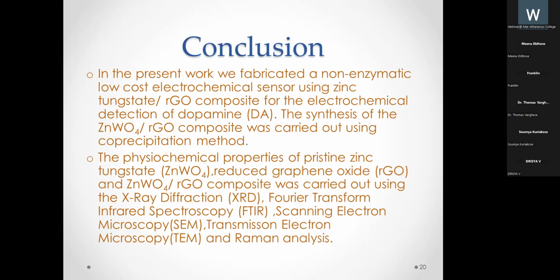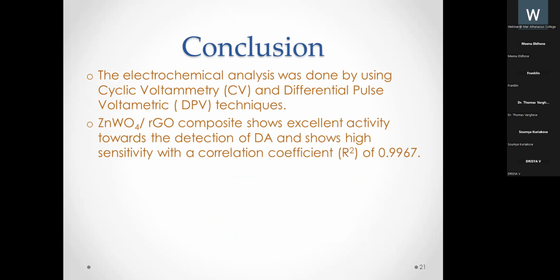The major conclusion which I have arrived at is that in the present work, we fabricated a non-enzymatic, low-cost electrochemical sensor for the electrochemical detection of dopamine. The synthesis was very simple, carried out using the co-precipitation method for the zinc tungstate RGO composite. The physicochemical properties of pristine zinc tungstate, reduced graphene oxide, and zinc tungstate composites were studied using XRD, FTIR, scanning electron microscopy, TEM, and Raman analysis. The electrochemical analysis was done using CV and DPV techniques, and it shows excellent activity towards the detection of dopamine and high sensitivity with a correlation coefficient R² of 0.9967.